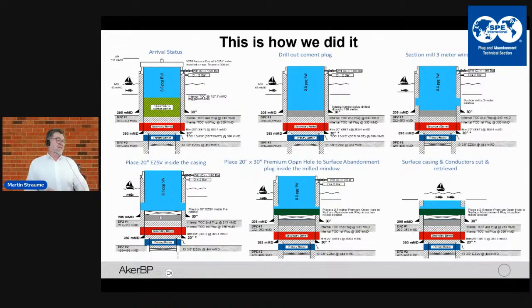We threw some sand on the bottom so the bismuth material shouldn't melt the plug. And then we poured bismuth material in there. Then we monitored the bismuth plug for some time and saw that we got to zero pressure buildup.